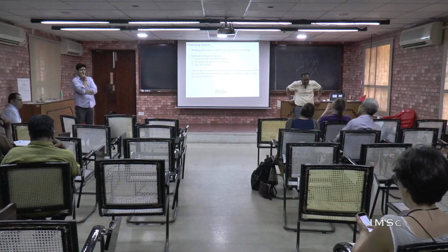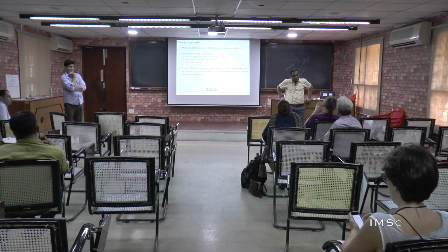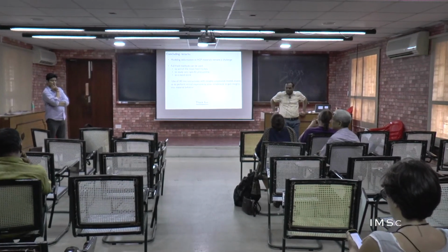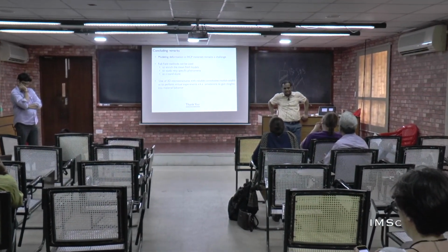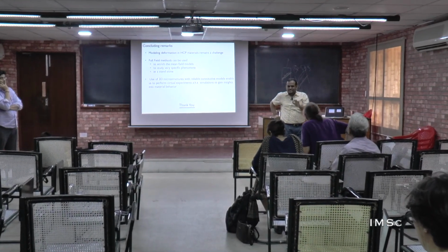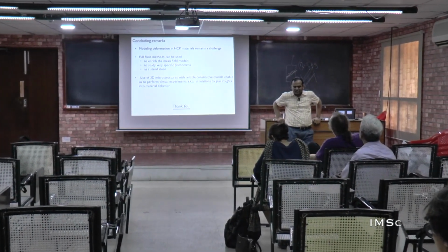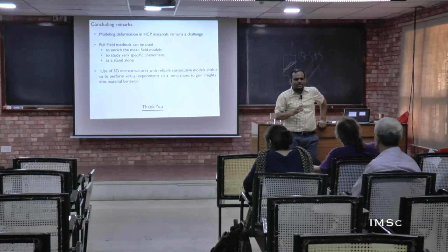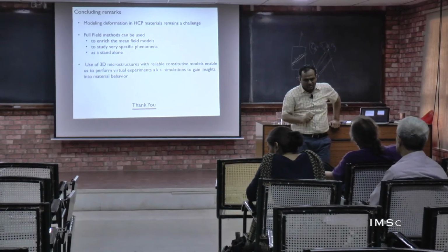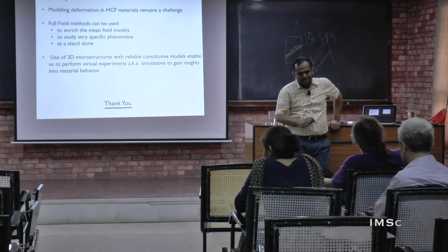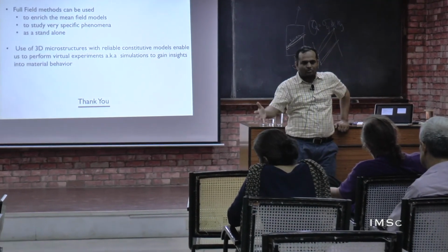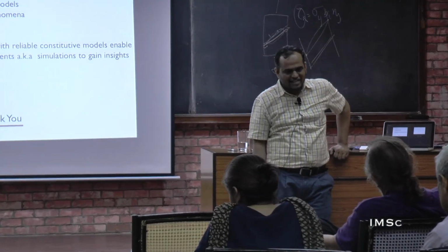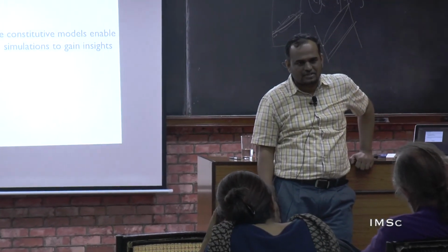Okay. And this is only possible for HCPs? You can also see it for FCC in some particular cases. BCC you do not tend to see. Very few BCC materials actually do it, but generally it is very common in HCP, and somewhat common in FCC materials with extremely low stacking fault energy. If you take copper or brass, you tend to see them. In orthorhombic materials, uranium for example, and beryllium, you see them. Ice also has a hexagonal crystal structure.